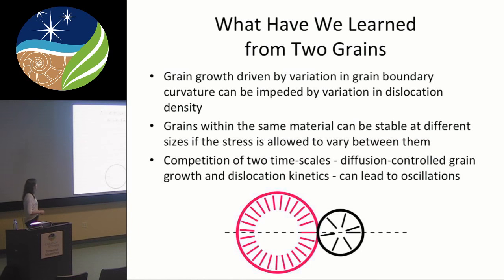That sums up this two-grain system. I hope I managed to communicate some of the most important behaviors we can see when involving grain size in this very simple two-grain system. Most importantly, you have two driving forces, grain boundary curvature and dislocation density, and they compete. Because of that competition, there is a possibility for a steady state, some mean grain size that you can observe through time.